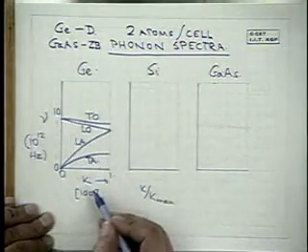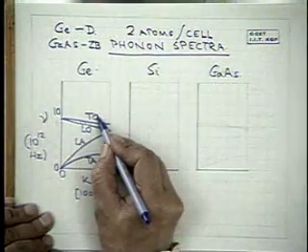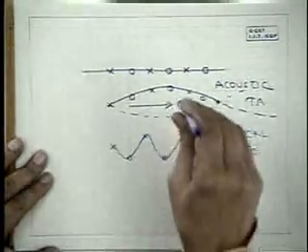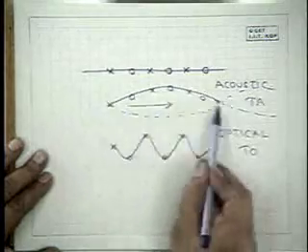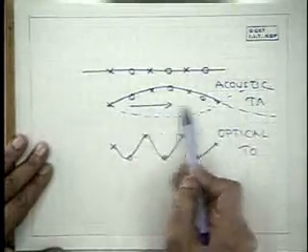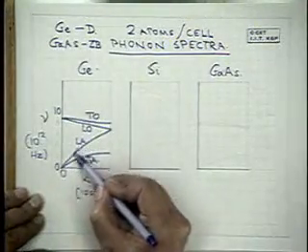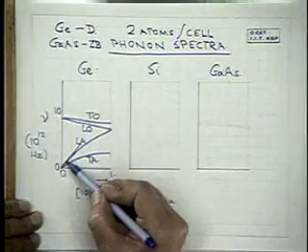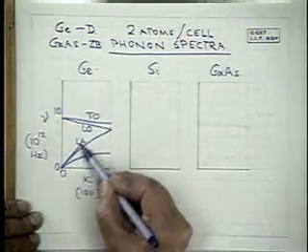notice that, as I said, there are two transverse modes, because the atoms can move either in this direction, in the plane of the paper, or perpendicular to this direction. So there are two transverse modes, whereas there is only one longitudinal mode. It's like a sound wave, which is a longitudinal motion. And incidentally, the slope of this LA curve, d omega dk, is nothing but the sound velocity in a particular medium. So d nu dk here is the sound velocity.